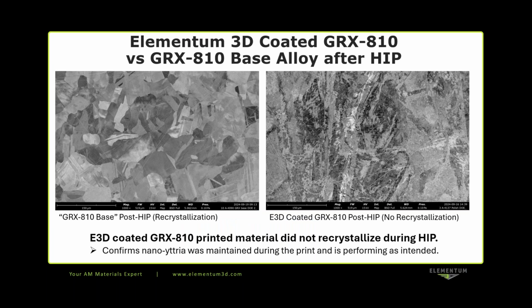And one of the other tests that we did, again at Tim's recommendation, is you can confirm that the yttria is doing its job by looking at the microstructure before and after hot isostatic pressing. At those high temperatures in the HIP, you'll get recrystallization if you don't have the yttria there pinning the structure and preventing that recrystallization. So you can see on the left, that's the recrystallized GRX 810 base material if you don't have yttria added. On the right, that is the same as-built microstructure that you get, but it's shown after HIP because it has the yttria included, and the yttria is doing its job. So this really just confirms that the yttria was maintained and is doing its job in the printed material.